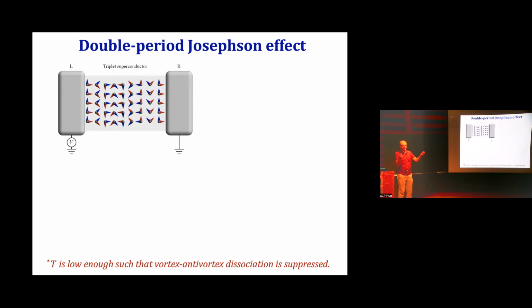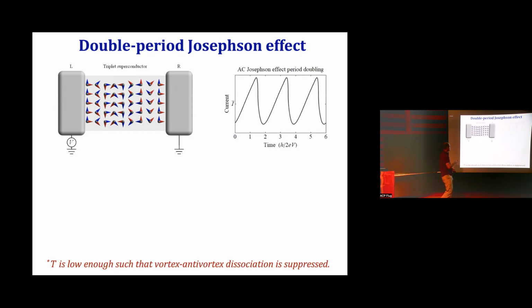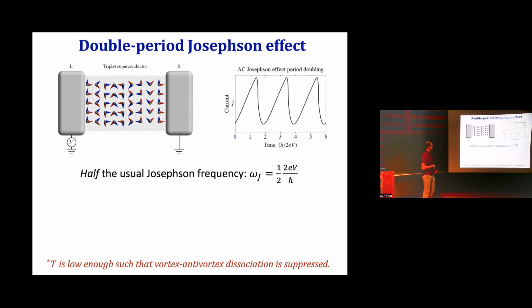In usual superconductivity, there's the AC Josephson effect. If you apply a voltage across a superconducting junction, the current oscillates with a universal frequency, which depends only on the voltage. Here, because of this Z2, whenever the superconducting phase winds twice, you can unwind it. That would lead to a double period of the Josephson effect. Some other interesting consequences: the critical current of such a superconductor would be mesoscopic, depending on system size. If you apply a magnetic field, it would become finite, because the in-plane magnetic field, through the Zeeman effect in the direction of magnetization, causes this to be a real robust superconductor.